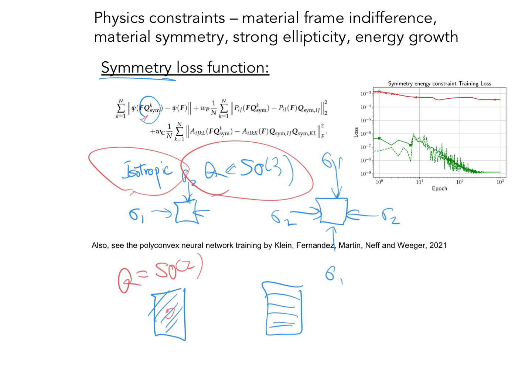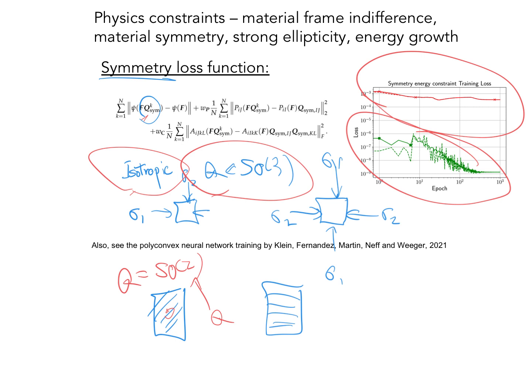And then you have to define particular rotations. So the rotation would not be any arbitrary SO3, but a subset of SO3. And for crystals, you have a lot of these rotation groups, monoclinic, etc., and if you want to model crystals, this becomes very important. You just need to find the corresponding subgroup in SO3 that obeys the symmetry. Symmetry needs to be explicitly implemented in our numerical experiments.